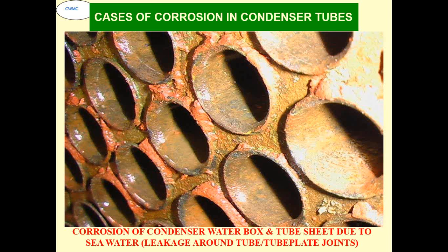A typical problem you see is severe crevice-induced corrosion as well as dissimilar metal welding galvanic corrosion at the tube plate of your heat exchanger. That is the most prone area, where the tubes are expanded and small crevices are formed in which the water goes, and a differential cell is created in terms of either differential oxygen or differential concentration of chemicals, and you get crevice corrosion there. Or because of the different tube sheet material and tube material, you can have galvanic corrosion and severe corrosion there. Third, in that area you can have a concentration of microbiological fouling, and microbiologically induced corrosion can take place all around that area depending upon the metallurgy.